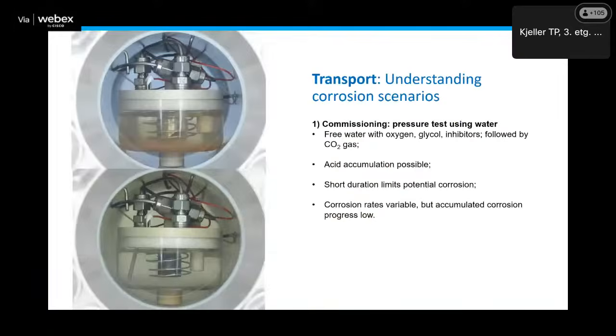And basically, at our corrosion department, my colleagues have been working on different scenarios during transport and understanding how corrosion can occur. So I have 4 slides here. The first slide, we see what can happen already during the commissioning. So when a new pipeline is built, you test it with water and glycol and inhibitors to see whether it's pressure tight, and that's being tested here in this setup where an electrode system is used to monitor changes in corrosion on the steel coupon in the center of the cell.